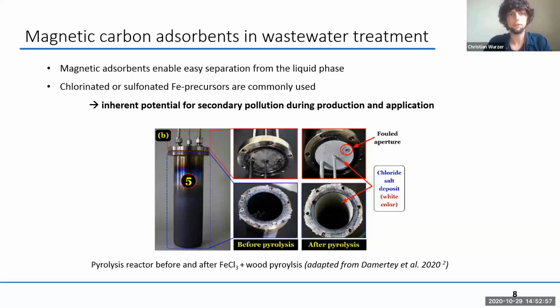So there's another problem with producing magnetic carbon adsorbents, which is that they're usually produced by the use of chlorinated or sulfonated iron precursors, so usually iron salts, different ones. And as we already can assume from the word chlorinated or sulfonated, they have an inherent potential for secondary pollution, both during the production and the application phase. And as an example, here's a picture from a recent publication from Damertey et al., who did iron chloride pyrolysis. And on the right side, you see the chloride salt deposits.